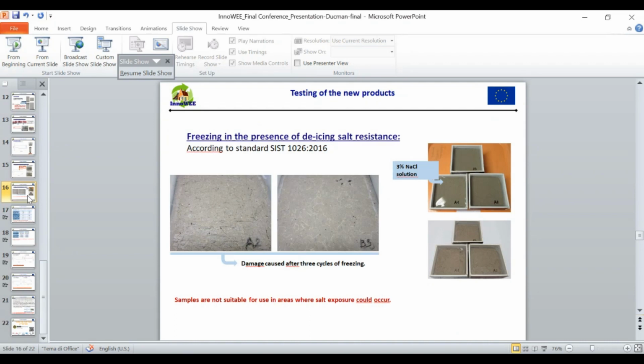In the case when such panels would be used in an environment with simultaneous action of salts and freezing, it's also recommended to do freezing tests in the presence of de-icing salt. This is not required by ETICS-004, but since we know that this might be a problem, we also introduced this method from the RILEM Technical Committee. We exposed samples to a 5% sodium chloride solution, but samples did not withstand these conditions because chipping and scaling of the material on the surface occurred, as you can see here. But this is good to know in advance, to avoid using such panels in, for example, marine environment, and so prevent certain damages.